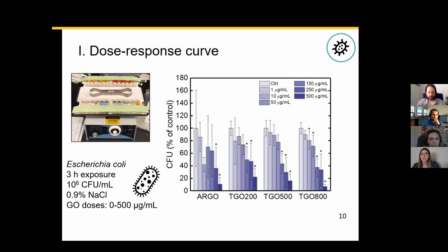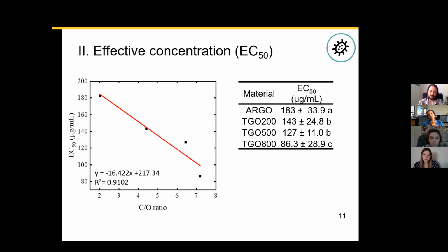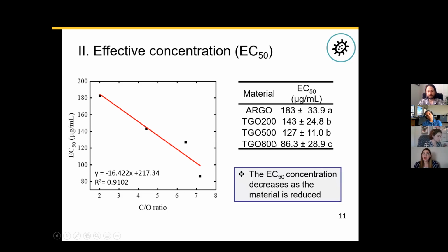Now, the first thing that we wanted to do was to generate dose response curves. We did this by incubating bacteria, in this case E. coli, with a wide array of concentrations of these materials. We see that each of these materials generates a different response at different concentrations. So to narrow down how these interactions happen, we calculated the effective concentration at which 50% of our bacteria responded to the material. In this case, we see a very strong linear relationship between the EC50 value and the extent of oxidation of our materials, where the more oxidized material, in this case as-received GO, usually requires a lot more material to reduce bacteria viability by 50%. And the most reduced material requires less.